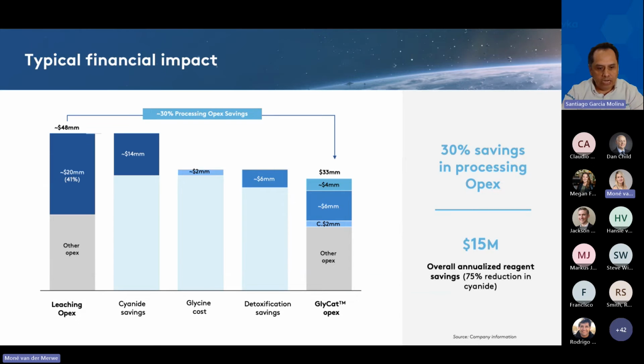The cyanide costs in the leaching OPEX represents around 41% of the total cost. Cyanide savings are around 14 million, as you can see in the second column, when using glycat. So the cyanide expense is reduced by 75%. Because glycat is used, glycine has to be added, but there are also other cost benefits in the detoxification process, saving another $6 million. Overall, this mine will save around $15 million every year after implementing glycat. And this calculation doesn't include any potential benefit because of the gold recovery, which has been seen in many cases.